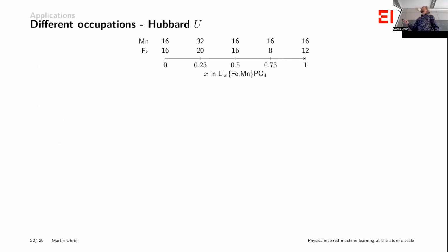So one thing I tried is, I took these olivine structures, LiFePO4, LiMnPO4, and these numbers represent the total number of training examples I have at each concentration of lithium. For each one, I'm going to take, for example, just one of these and train the neural network model on, say, x equals 0, and then ask it to predict all the rest. And take the other one and ask it to predict all the rest. And I'll average over all those, and then I'll show it 2 out of the 5 of these, and then I'll show it 3 and see how it is able to extrapolate.